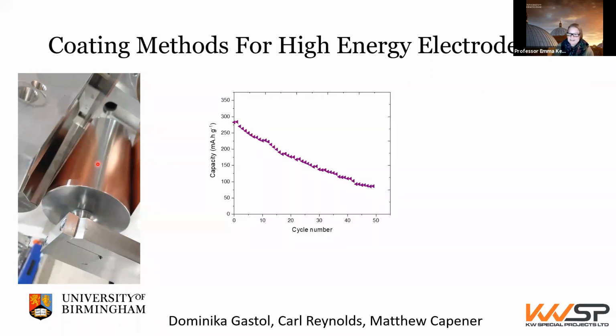This gives you an example of one of the performances of those materials. This is a graphite material. Its theoretical capacity is 372. And from this particular thick electrode, we're aiming for about 3.3 milliamp hours per centimeter squared coating here. You can see we get quite a fast fade rate. And without an awful lot of optimization, this is what we get for the high coat weight electrodes.